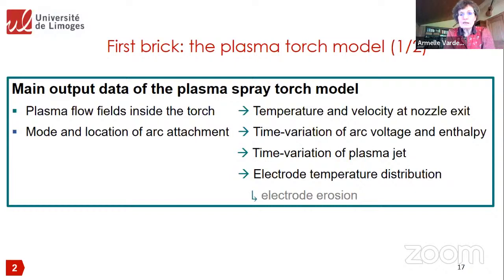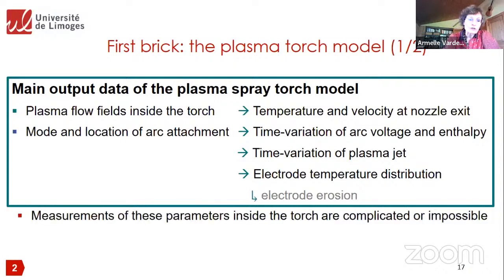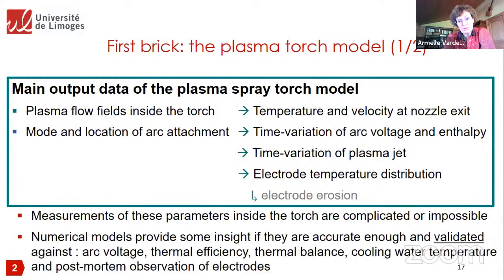This will make it possible to predict the time variation of the arc voltage and so the enthalpy input to the gas, but also to predict the time variation of the plasma jet and the electrode temperature distribution. And this is the gate open to the prediction of electrode erosion. If you think about these data, they are not easy to measure inside the plasma torch, and even some are impossible to get. So we have to validate our prediction.